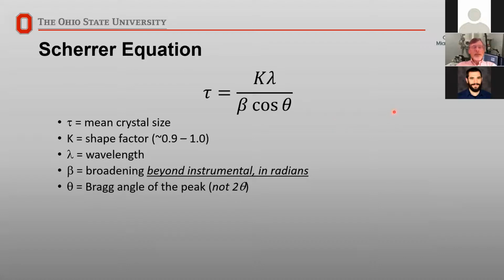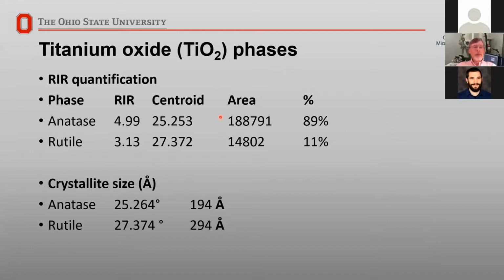So going back to that titanium dioxide sample that we had earlier, not only did we calculate the amount of material, we could actually calculate the crystal size. And based on the broadening, we find that the anatase crystals came out quite a bit smaller, only 2/3 the size of the rutile crystals. So this will very much affect the properties of the crystals that you have. If you're interested in doing catalyst work, or in the case here, this was a sunscreen, these crystals will absorb differently depending on their size. So this is an important parameter for many materials people.